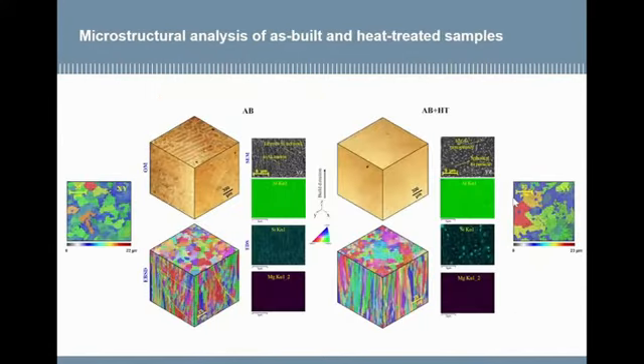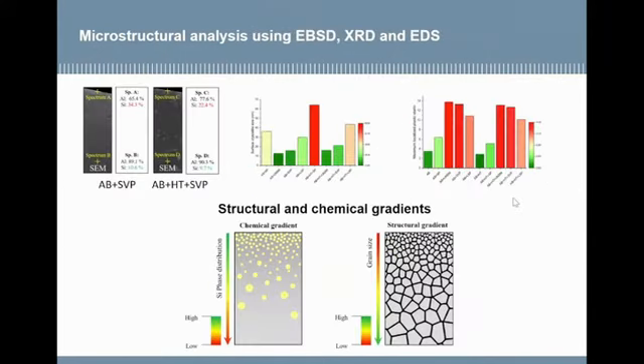Very briefly, just to show you the results of the heat treatment that was applied on half of the samples, we are starting from a very irregular structure in terms of the microstructure of the samples, depending on the build direction and the section that we consider with respect to the build direction. And after the heat treatment, these laser tracks are completely fading. The distribution of Si particles in the aluminum matrix is becoming much more regular. So we are somehow eliminating the anisotropy in terms of microstructure with the applied heat